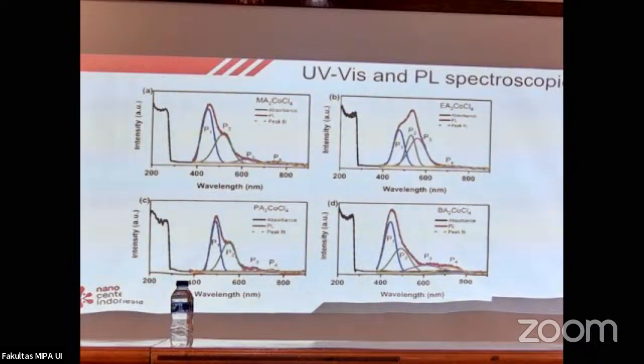So I recall again from our, unfortunately I didn't show the XRD. From our XRD, it turns out that the crystal, especially for the EA case, is not really a good crystal. So we basically relate the situation from the atomic arrangement, that the P3 contribution comes from the defects. And also happening in another case.